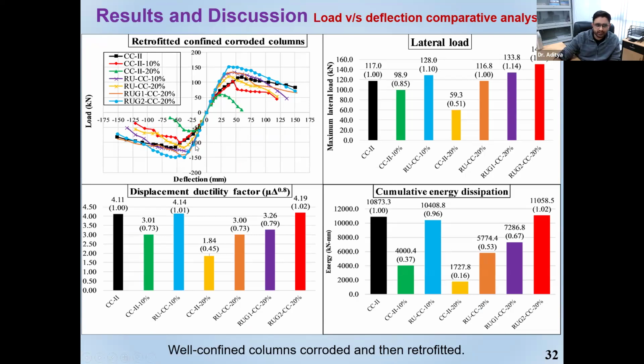So here I have compared the backbone curve of those hysteresis responses just to give you a visual comparative understanding. Here you can see the lateral load, or the flexural strength, of the column is compared. The control column, if I assume it to be 1, is the normal column which has not been corroded, which has been designed as per the latest Indian guidelines. It is supposed to be 117. So that was the flexural strength that I got for a normal column which is not corroded. Then when it corroded by 10%, you can see that there was a reduction of almost 15%. That means now it is only 0.85, 98.9 kilonewton, which is 85% of the control.